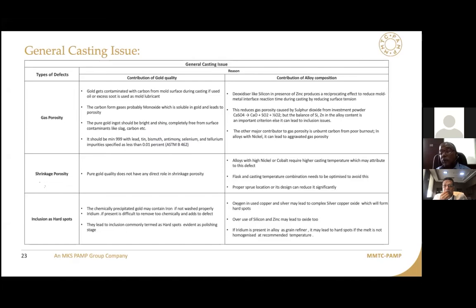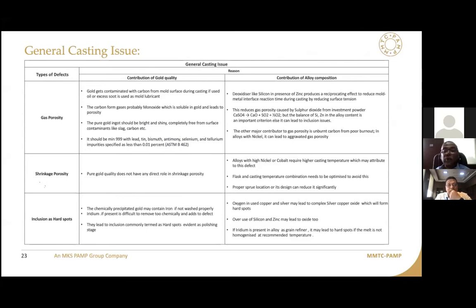From the alloy, we can say that the copper needs to be deox quality. That means the copper needs to have less than 10 ppm oxygen, while the silver that you use should be of electrolytic origin and should have less than 50 ppm oxygen, so that there is no oxygen present where the copper can get oxidized and included as oxide. And if you are using iridium in your alloy, then the iridium very likely will form clusters and will lead to this hard spot. So this is where the inclusions can come from.